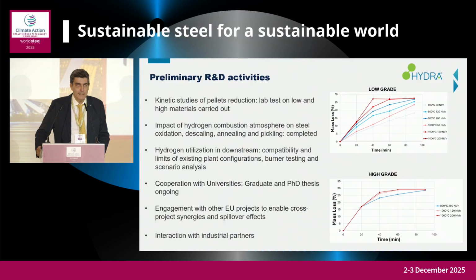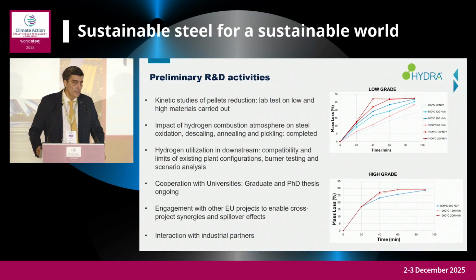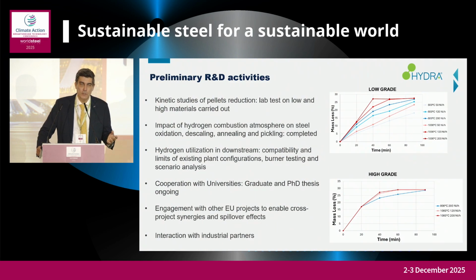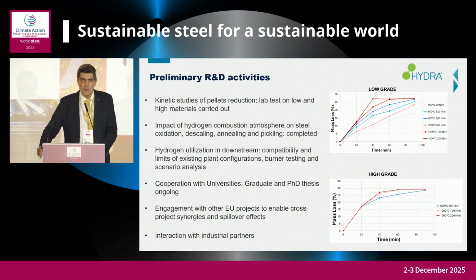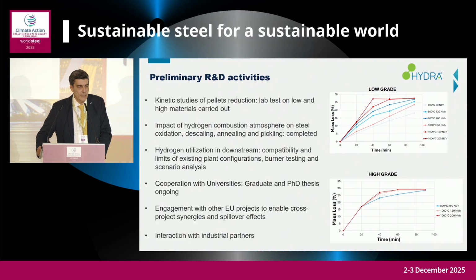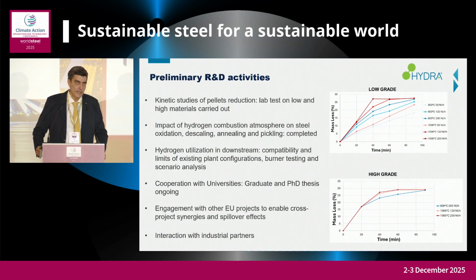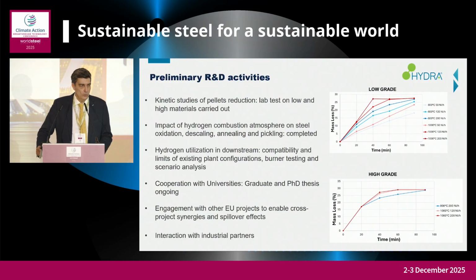We performed a lot of tests to determine the impact of water at different temperatures on the oxidation rate. We performed experiments from 900 degrees up to 1,200 degrees at different temperatures and with different steel grades. And we are also just starting an activity to study the compatibility and the limits of existing combustion systems working in blends with hydrogen and natural gas. We also started a cooperation with the universities. 3 graduate theses are ongoing, and new ones are going to start. And we are also starting engagement with other European projects to enable synergies, spillover, and the exchange of experience, and also interaction with industrial partners.